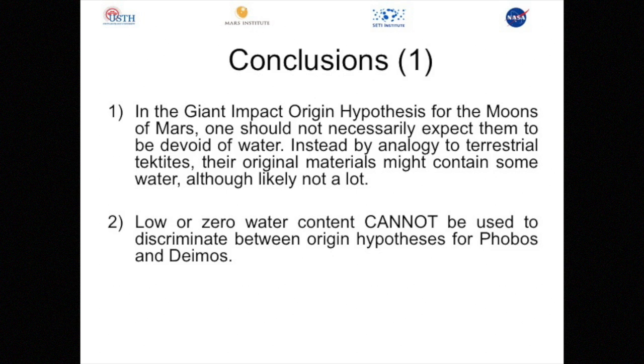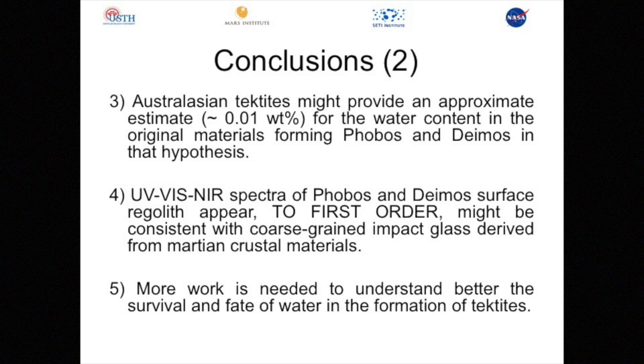All right, so here's the conclusion. In the giant impact origin hypothesis for the moons of Mars, we should not necessarily expect them to be devoid of water. Because of our examination of tektite, the original material might contain some water, although it's likely not a lot. It implies for future missions, for example JAXA's Martian Moons eXploration, that low or zero water content cannot be used to discriminate between origin hypotheses for Phobos and Deimos, although we need to do more work to confirm that. Also, Australasian tektites might provide an approximate estimate of about 0.01% for the water content in the original material of Phobos and Deimos in that hypothesis.